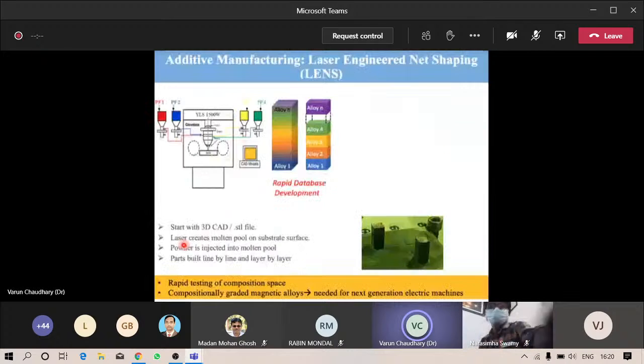So let's discuss how additive manufacturing is suitable to print graded samples. We are using Laser Engineered Net Shaping, the so-called LENS technique, to make this kind of sample. So this is the schematic here. We have multiple powder feeders, and by changing the feeding ratio, we can change the composition. This powder comes through the nozzle and is melted by the laser. And by changing the ratio, we can either print a continuous change from the bottom to top, or we can print a discrete change. It depends on the programming you do.